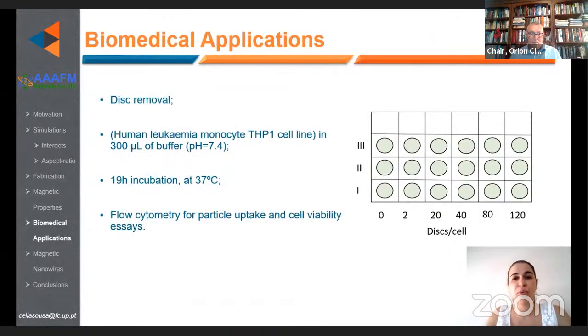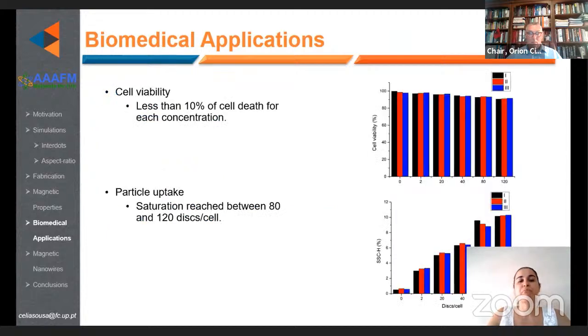Finally, the nanodiscs were removed from the substrate by an etching process of the aluminum layer, and the nanodiscs were dispersed in a buffer solution and incubated with the human leukemia monocytes to evaluate the internalization of the nanodiscs by the cells and their biocompatibility.